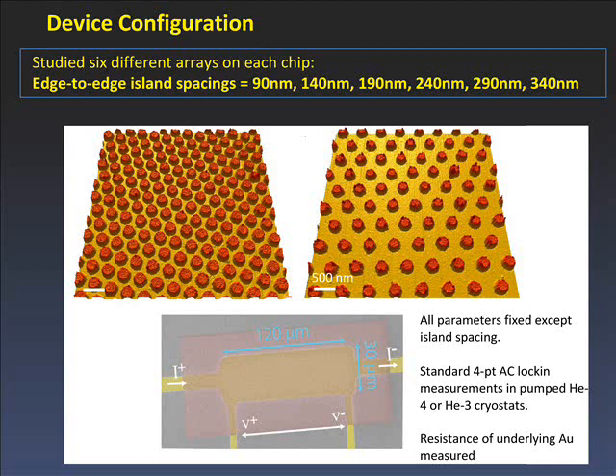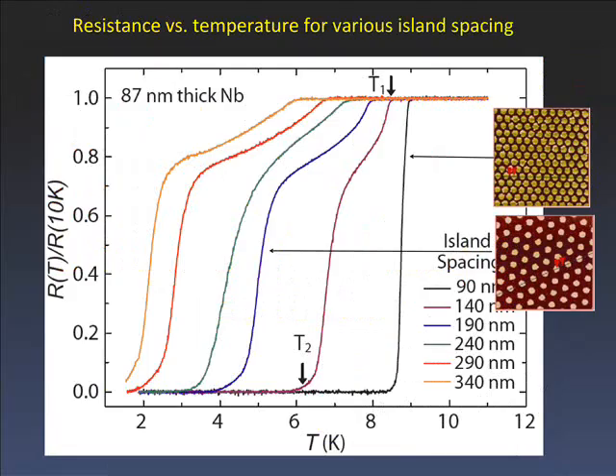The first set of experiments: we took a chip, did everything identically, but changed the island spacing, giving us six different devices with different spacings but everything else identical. We do standard four-point AC lock-in measurements at low temperatures and measure the resistance of the gold to see where we see supercurrents. We indeed see transitions — in fact two-step transitions — and the transitions go to lower temperatures as the island spacing is increased, as you'd expect.